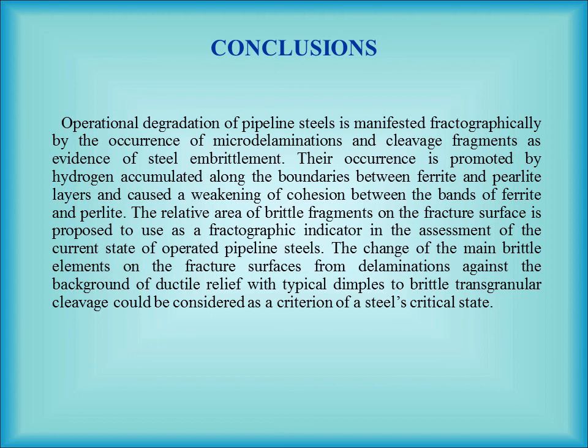The change of the main brittle elements on the fracture surface from delamination against the background of ductile relief with typical dimples to brittle transgranular cleavage could be considered as a criterion of a steel's critical state.